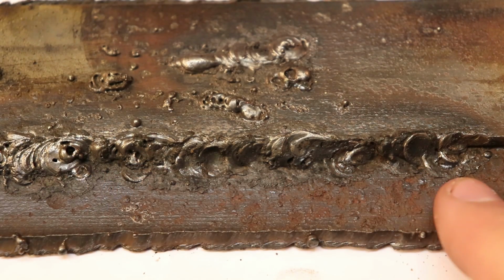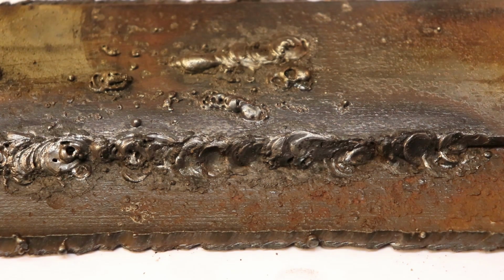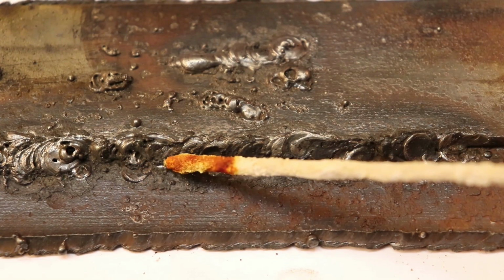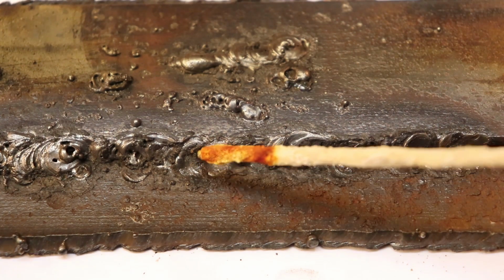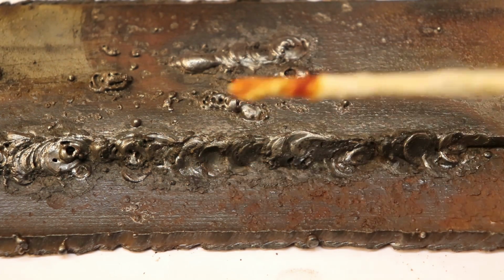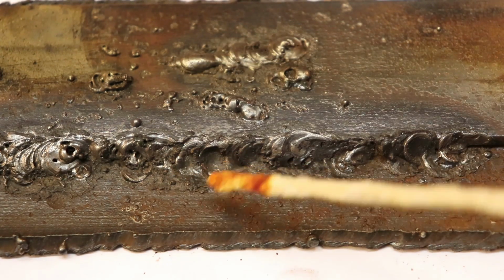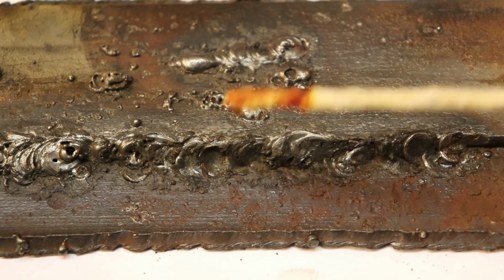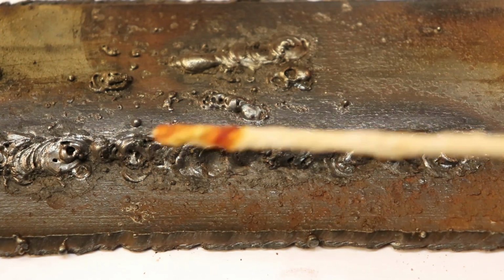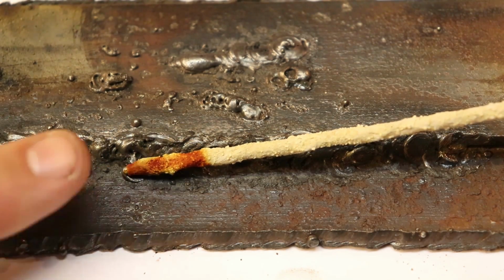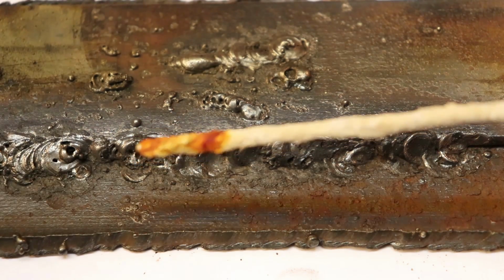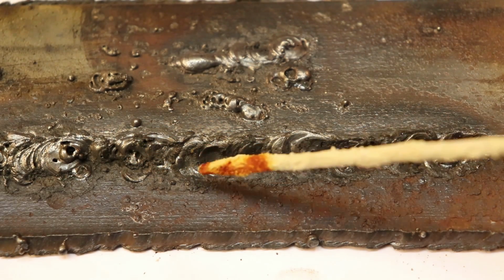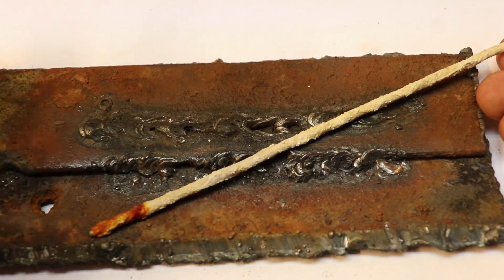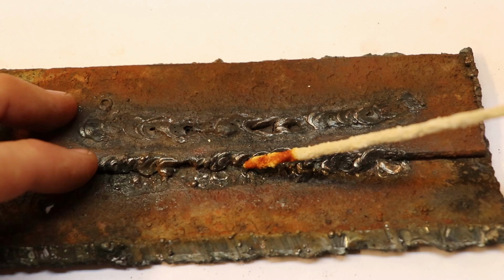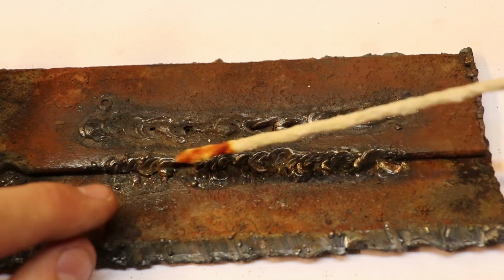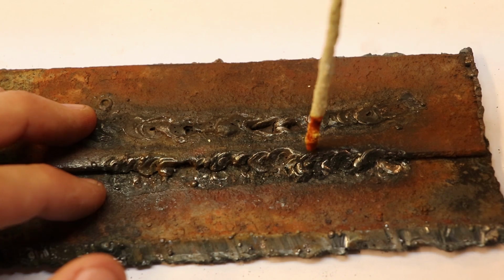So here's more of a close-up on these good welds. And actually I found with the welding rod that I made, I had to go at quite an angle, maybe like a 45-degree angle, which I think is probably standard for most types of welding. However, some commercial rods advertise that you can weld with them in any position. Now, I don't think this is the case with these particular rods. These rods that I made myself are best when welded with an angle. So yeah, all I'm saying is I had more control and an easier time welding when I welded with these rods at an angle compared to straight on top.